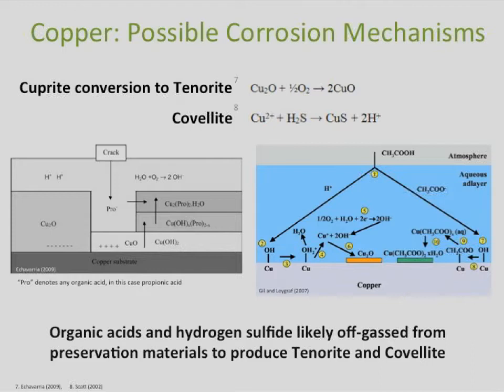So I didn't mention it, but basically all materials, and definitely metals, have these monolayers or multi-layers of water on the surface. And so the metals are in both the ionic and the metal form on the surface in a small equilibrium for silver, copper, and lead. They're hydrated or have hydroxyl groups on them, and this is where all of these gaseous materials can come in and interact on the surface.